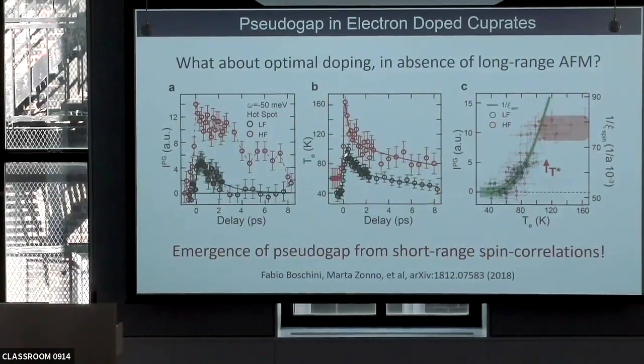extract an effective temperature, and replot this data versus delay and electronic temperature. And then finally take the intensity that he observes per the pseudo gap and plot it, the intensity of the pseudo gap versus electronic temperature. And when he does that, the scatter plot are the data that Fabio has obtained. You see that the pseudo gap grows as a function of temperature and then saturates.